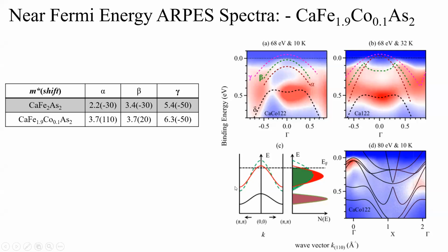When I dope the electron at this position, I see that these bands are now renormalized, so the bandwidth is small and the density of states will go up. Since the density of states is high, I can put more electrons within this small region. So there is a possibility that while filling these states, the Fermi energy in these two cases will remain at the same position, leading to negligible change in the binding energy position of the higher binding energy states.